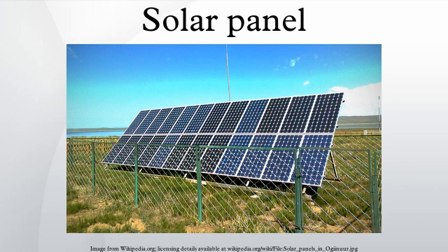A research by Imperial College, London has shown that the efficiency of a solar panel can be improved by studding the light-receiving semiconductor surface with aluminum nanocylinders similar to the ridges on Lego blocks. The scattered light then travels along a longer path in the semiconductor, which meant that more photons could be absorbed and converted into current. Although these nanocylinders were used previously in which aluminum was preceded by gold and silver, the light scattering occurred in the near-infrared region and visible light was absorbed strongly. Aluminum was found to have absorbed the ultraviolet part of the spectrum, and the visible and near-infrared parts of the spectrum were found to be scattered by the aluminum surface.